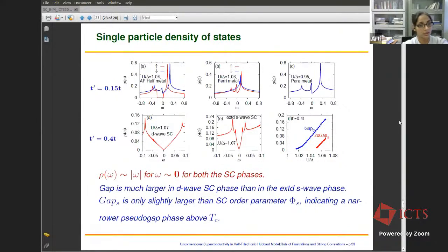The superconductivity will be killed by loss of coherence as we increase the temperature, and there will be a depletion in the density of states even above TC because of the Cooper pairs which will survive even for T greater than TC. And the pseudo gap phase for the D-wave superconductor should be much larger than the pseudo gap phase for the extended S-wave superconductors, because the gap for the extended S-wave superconductor is closer to the superconducting order parameter compared to the D-wave superconducting phase.